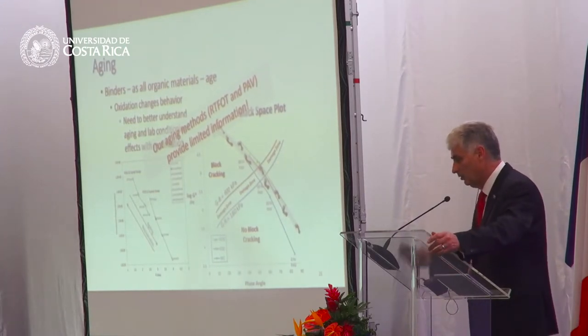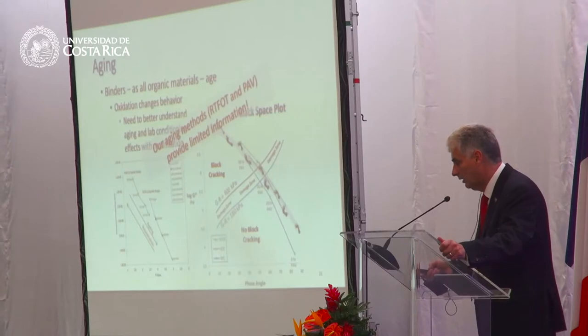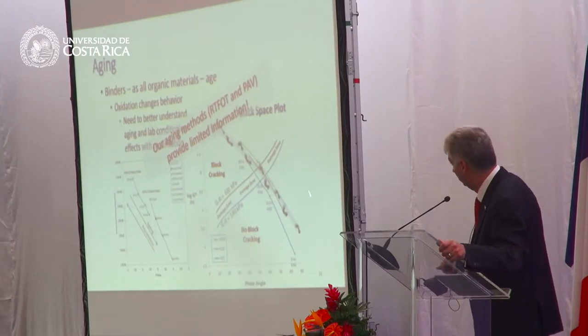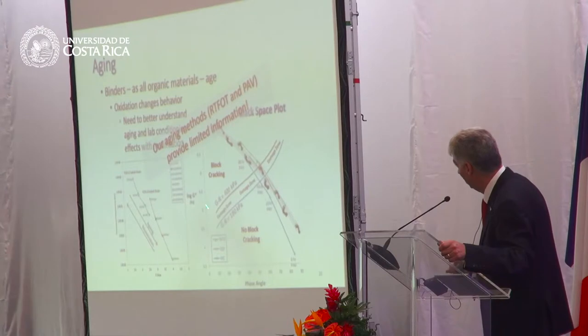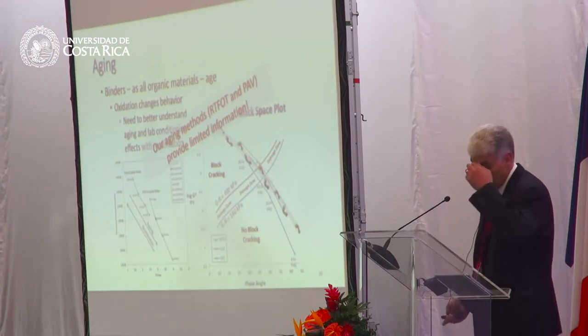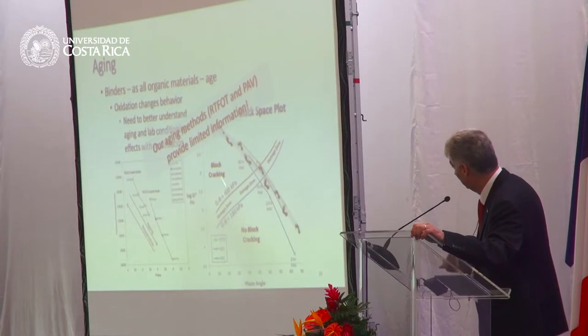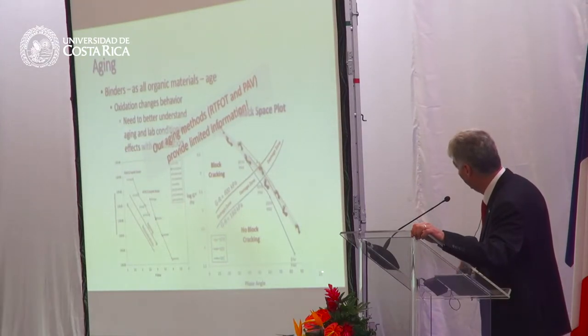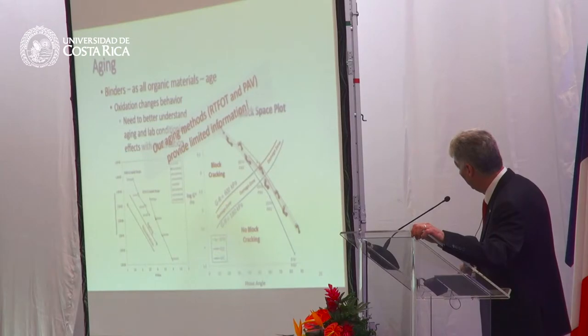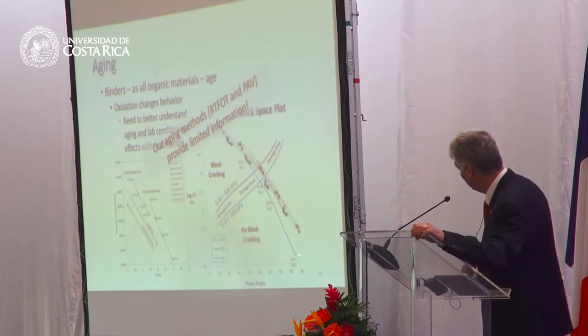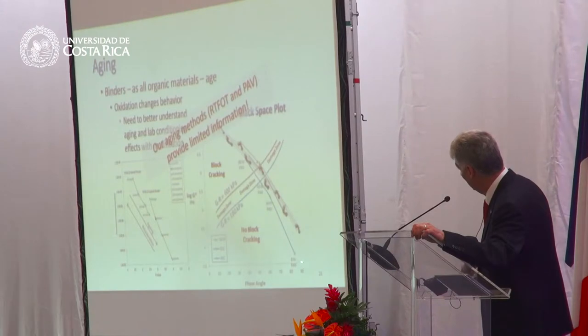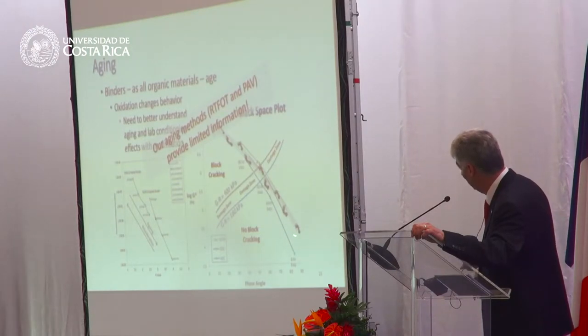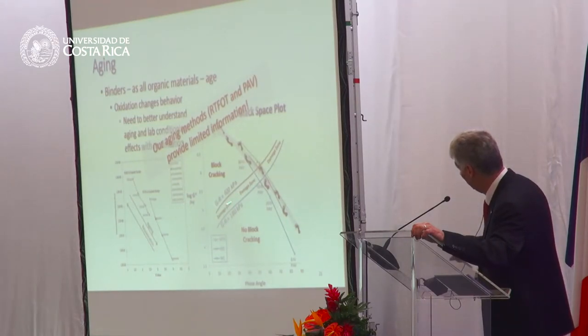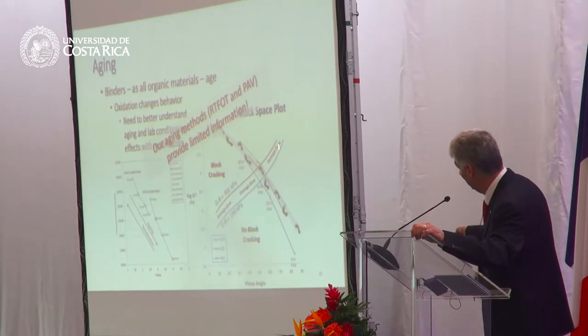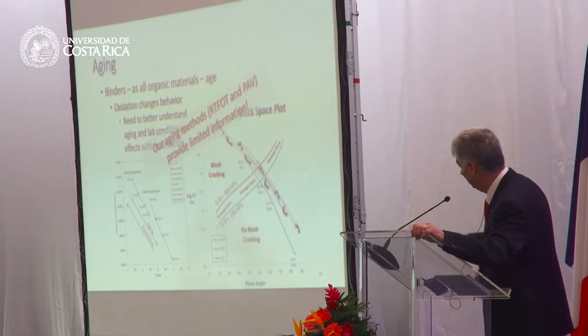As materials age, we'll see that oxidation increases. This one is looking at Glover-Rowe on this axis here. Glover-Rowe is a parameter which includes the G star and the phase angle. So on this plot here, you'll see G star and phase angle. And this is looking at one of those same binders on the previous slide. As that material ages, the material will get stiffer, the G star will increase, the phase angle will reduce, and eventually it will cross this damage zone. Here we have no cracking, and here we have cracking, and the material will age and crack.